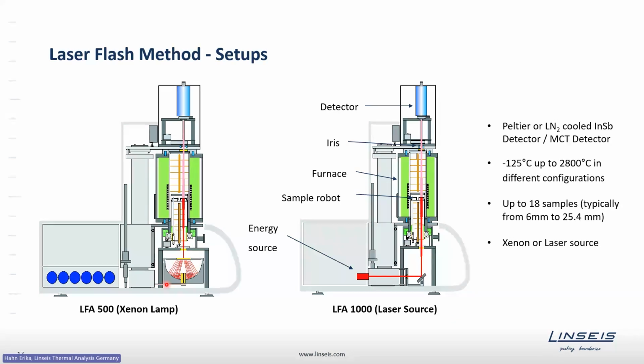has a lower pulse energy compared to the laser source, so it depends on the kind of materials which we want to investigate, which type of model fits the best. But basically, both setups are similar. So we have on the bottom each the power source, then we have the furnace, where the sample robot is located. So we have here different sample robots, up to 3 or 6 samples. Also the furnace types, there are a lot of different types, going from minus 125 degrees Celsius up to 2800 degrees Celsius, depending on the furnace type.